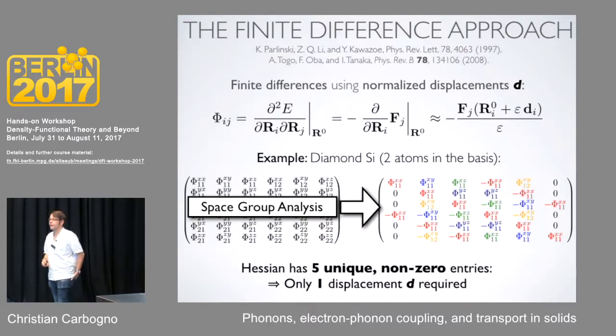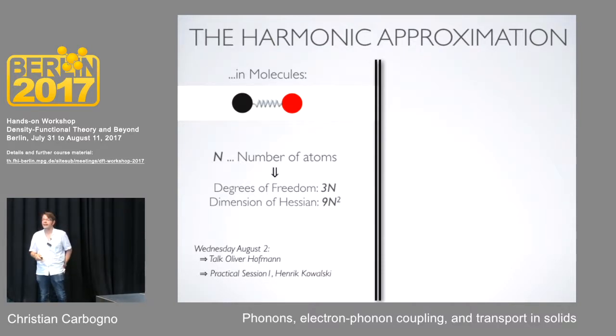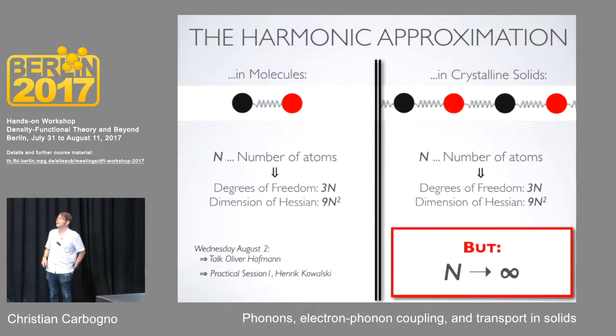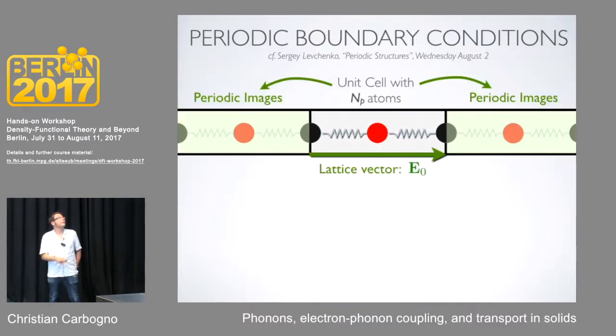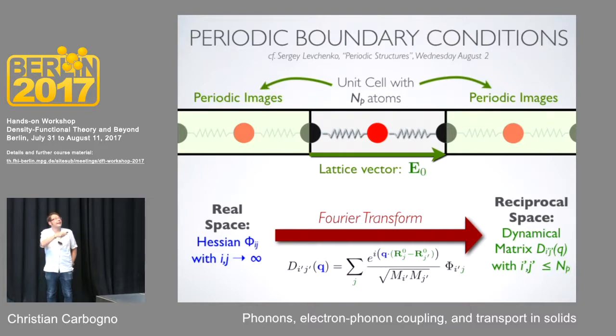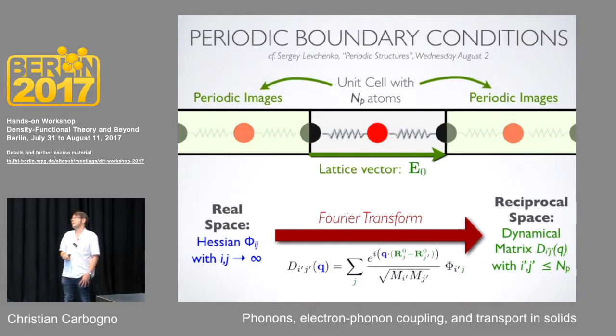Once you have the Hessian, you can compute the vibrations — this is conceptually very similar to what you have done in the practical session one for molecules. You have N atoms, 3N degrees of freedom, and a Hessian that scales with 9N². But if you go to a periodic solid, N goes to infinity, so you have to use the reciprocal space representation to circumvent this problem. For a linear chain of atoms with one unit cell connected by lattice vectors, the real space Hessian with i and j going to infinity can be Fourier transformed back to the unit cell, giving a dynamical matrix where i and j scale with the number of atoms in the unit cell, and a continuous variable Q describes how properties change in the Brillouin zone.